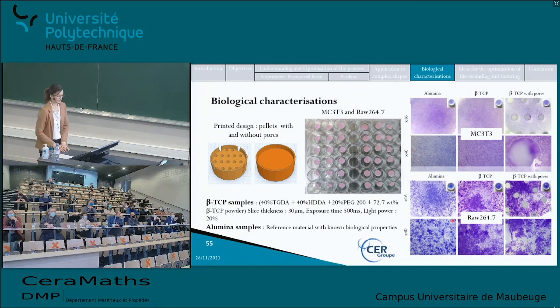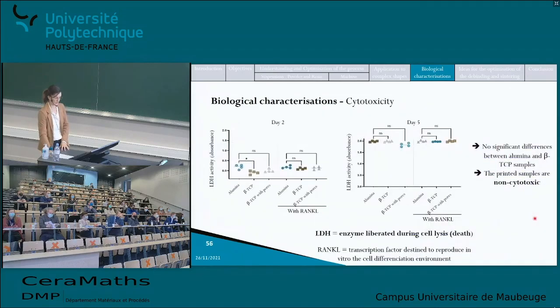So then the next step was to evaluate the cytotoxicity of the samples. So on all the experiments, there are some reference samples and some samples that are marked with RANKL. So this is a transcription factor that is designed to reproduce in vitro the cell differentiation environment. However, it does not impact the cytotoxicity measurements or the cell proliferation measurements. So here, the LDH activity was measured after 2 days of culture and after 5 days of culture. And the LDH is the enzyme liberated during the cell lysis, the death of the cells.